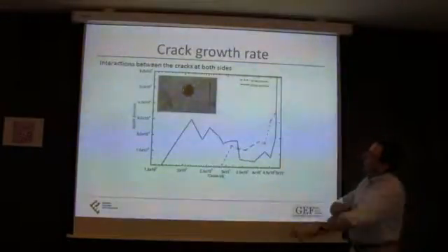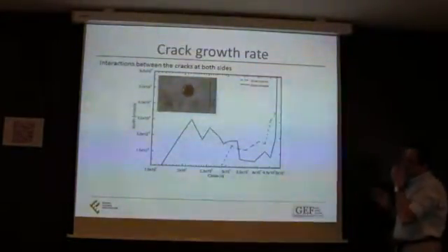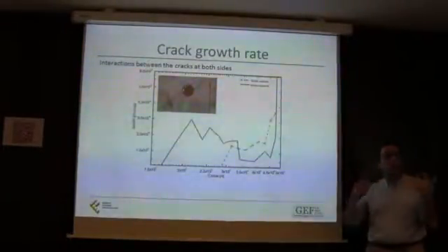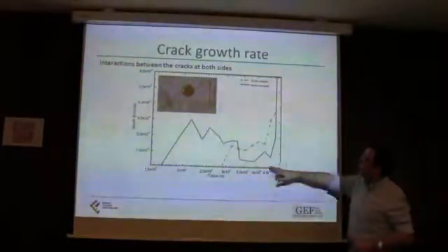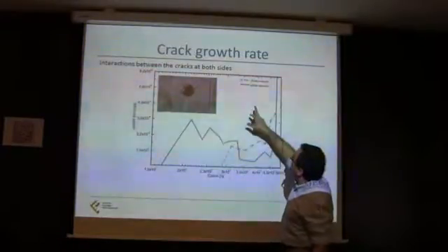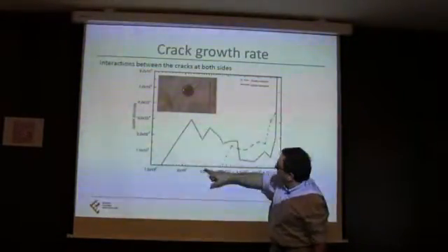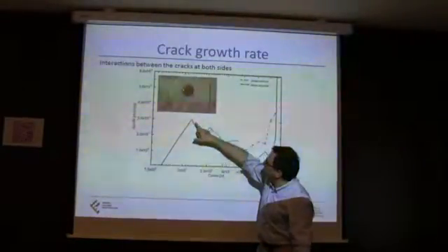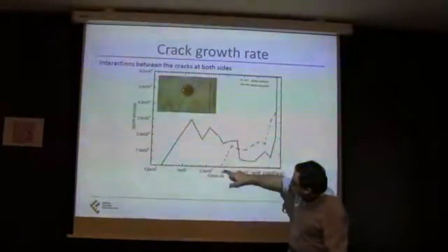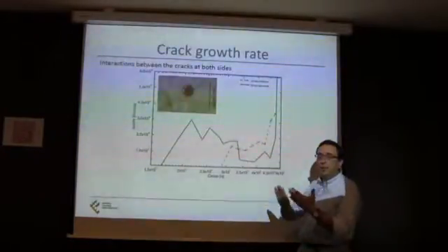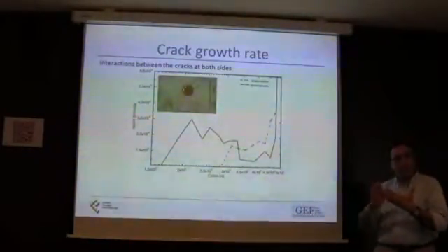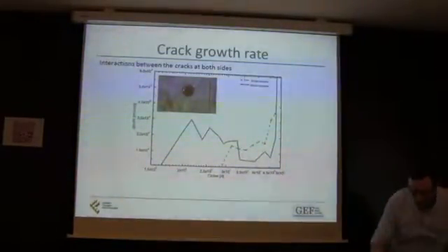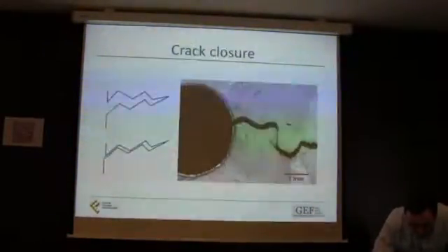We also found quite curious behavior: you can see a kind of interaction between the two sides of the crack. In here, this crack started growing on the right side, while the one on the left was stopped. But then when the crack growth rate of the one on the right diminished, this suddenly started growing. It's like they are not growing at the same time. It's like one is waiting for the other to stop to start growing, which is quite interesting.